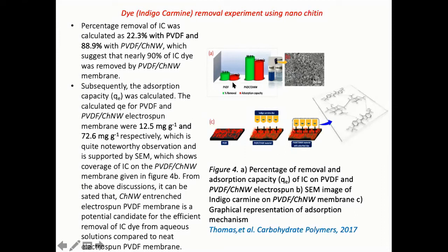This is a very interesting result. If you use the commercial filter PVDF, the percent of removal is only 23%. But if you combine PVDF and nanochitin together, look at the removal efficiency. The dye could be removed up to 88.9%. So this is the beauty of combining nanochitin and PVDF.